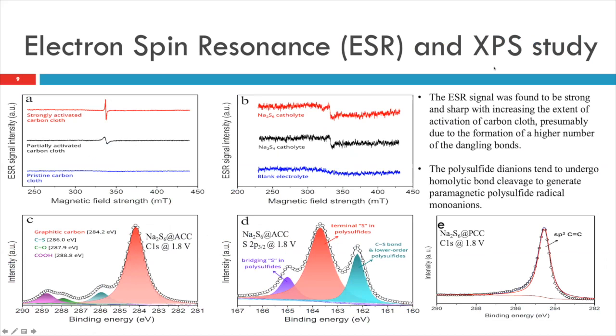Okay, so we did not stop there. We also worked on ESR, which will tell you whether radical formation is happening or not. We saw that on the pristine carbon, that is the carbon cloth, there is no free radical because we have not created any dangling bond. When it is partially activated, we started seeing the signal coming, which shows that free radical is formed. When it is strongly activated, you can see a strong free radical signal coming from the carbon dangling bond. And at the same time, when you look at the electrolyte system, which gives you the S3 monoanion, you see that there is also a peak.